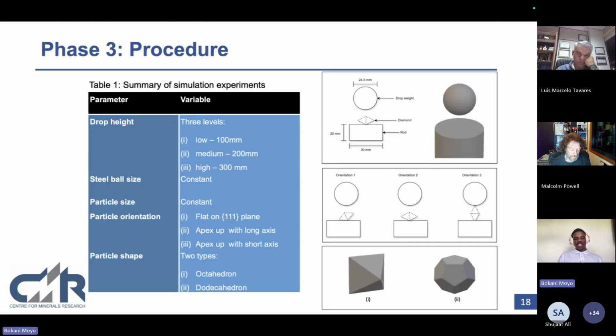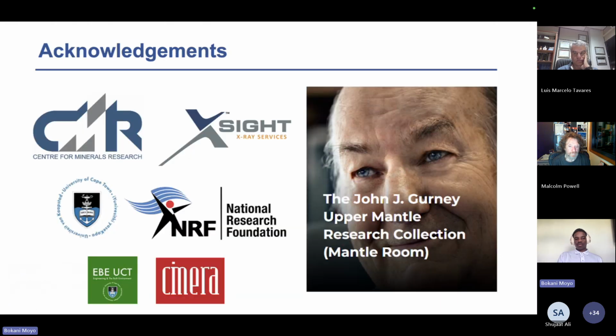And then phase 3, this is where we do our DEM simulations. And so we have a range of parameters that we're going to investigate by keeping a few parameters constant, which is the steel ball size and the particle size. We'll then employ varying drop heights, different orientations. So where it's flat on its 111 plane, or when the apex is up, as well as look at the 2 shapes. So you have an octahedral shape and a dodecahedron shape. So this is the plan going forward.